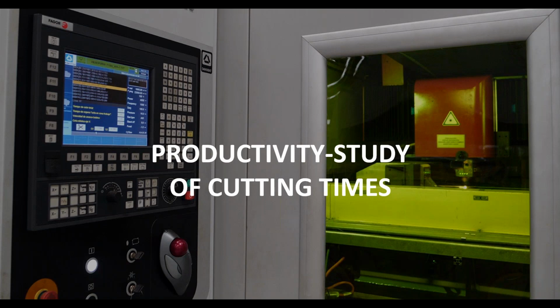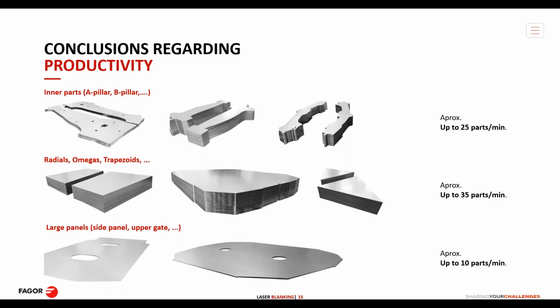We go through the productivities that can be achieved with laser technology. With the laser technology, we have divided the parts into 3 different groups. Firstly, we would have the inner parts, pillars, B pillars, and other reinforcement parts that could achieve up to 25 parts per minute throughput. Then there would be some simple blanks like radials, omegas, trapezoids. Those are quite fast parts, up to 35 parts per minute. And finally, large panels like side panels, up to 10 parts per minute.